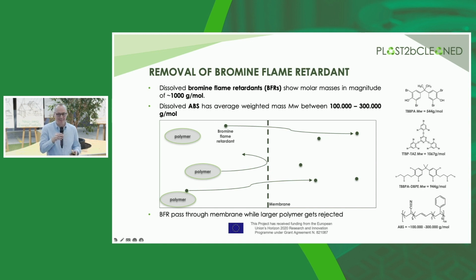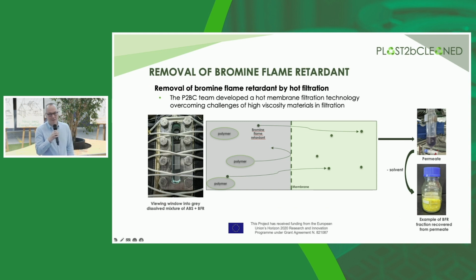Well, in theory, it's very nice. In reality, I think in the audience there might be some people who also worked with dissolved polymers. It's a very tricky subject to technically handle, but the team of Plast2bCleaned developed a hot membrane filtration technology that overcame these challenges of a very high viscosity material that tends to form gelation, gel-like material. On the left-hand side of the picture, you see this gray dissolved material containing the polymer and the bromine flame retardants. And on the right-hand side, you see a quite clear permeate. That is the material that goes through the membrane, and the recovered sample of bromine flame retardant, in this case from the reference samples.